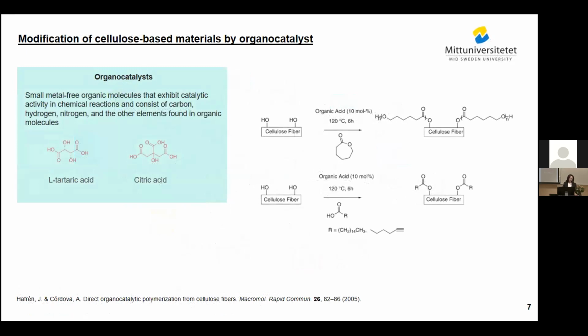In 2005, Hafren and Cordova did the esterification of cellulosic fiber using organic acid, direct esterification, or ring opening polymerization. Having this knowledge in the group, then in my thesis, I used this organic acid, mostly L-tartaric acid and citric acid, to modify cellulose and nanocellulose.